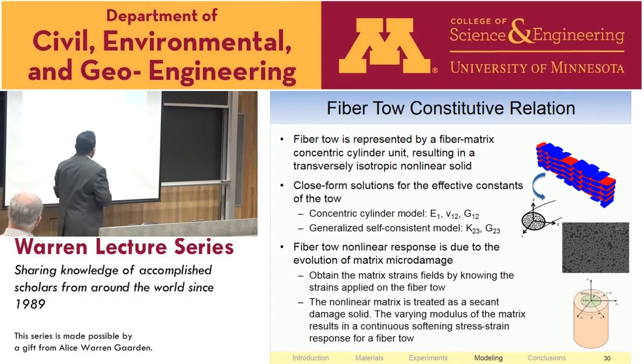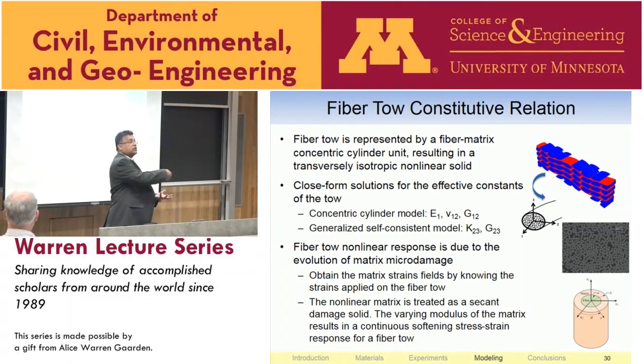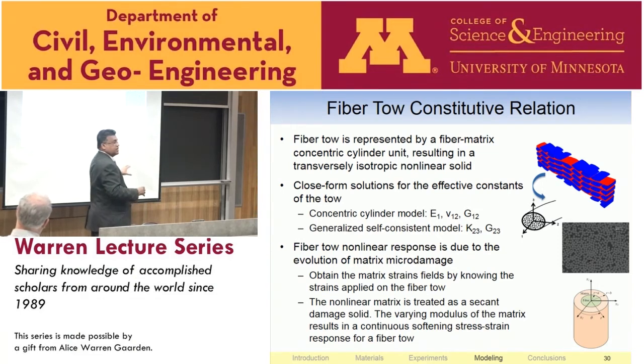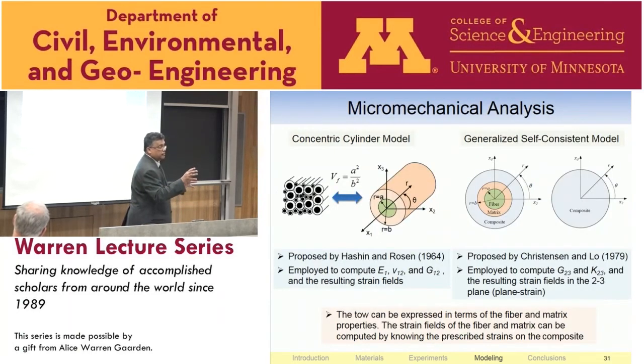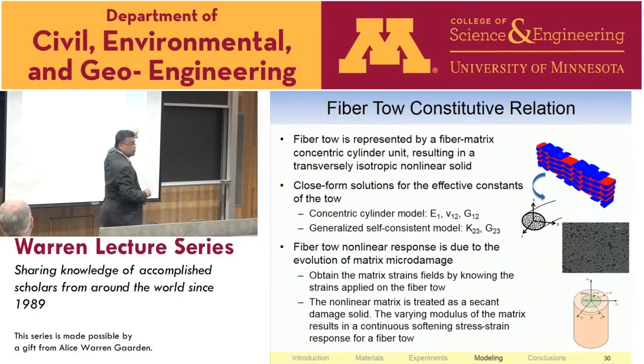All right, so for the tow, we used a representation of what we call the concentric cylinder model, which is a representation of a tow. And the nice thing about this is that instead of just using the tow to get the properties, what we do is we solve, given the state of strain outside a concentric cylinder, we solve for the state of strain inside the cylinder, in the matrix and in the fiber. And then we used a secant approach to upgrade the stiffness of the matrix, and the fiber remains elastic throughout, but the matrix changes based on its equivalent stress law. And then we used a multi-scaling there, where at each integration point, this cylinder is situated in the tow. So you calculate that. But the advantage is that it is not done numerically, it's done analytically. So the subscale calculations are analytical closed form in a secant sense.